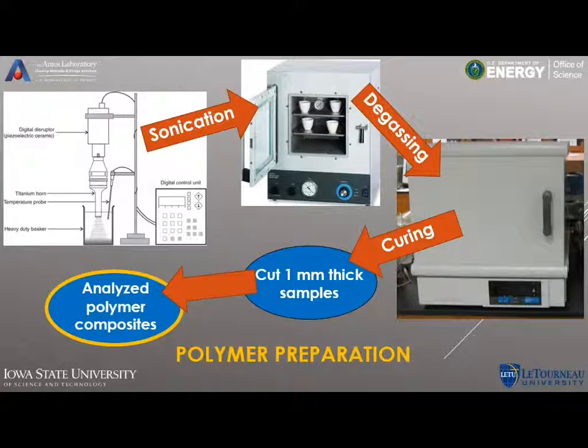After that, we poured the liquids with the filler material in them into rubber molds and placed them in a temperature-controlled oven, an isothermal temperature-controlled oven. And this heated the samples for several hours at different temperatures, first at a lower temperature and then at a high temperature, and that effectively cured the sample, or did what's called curing. In curing the sample, it basically just solidified it, so it polymerized the monomers into the full chain.